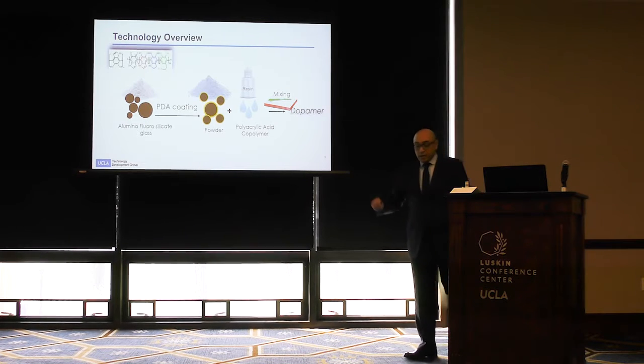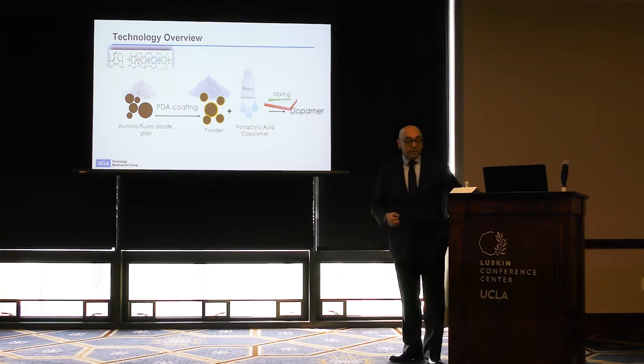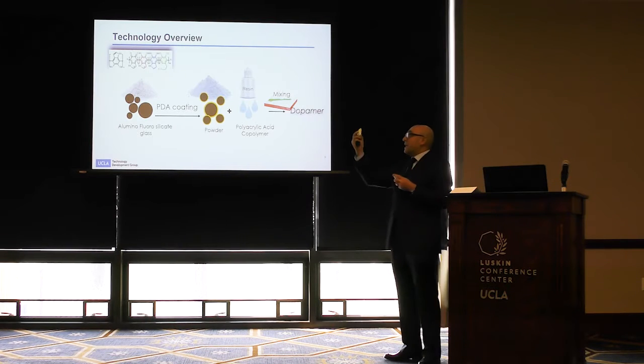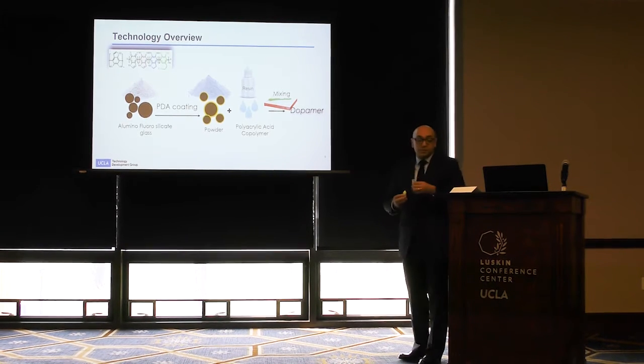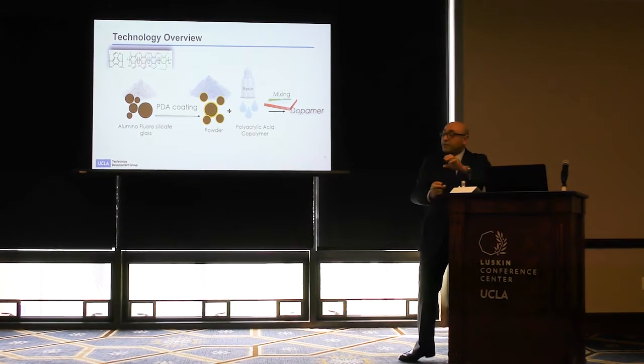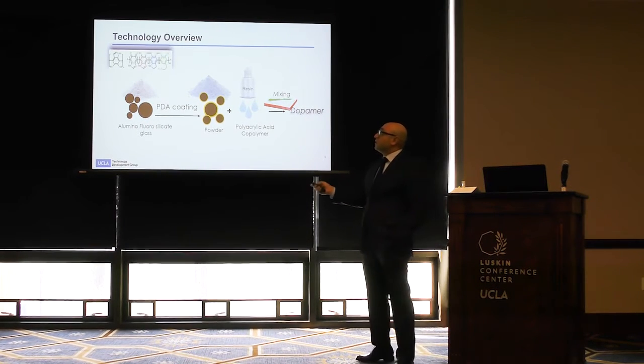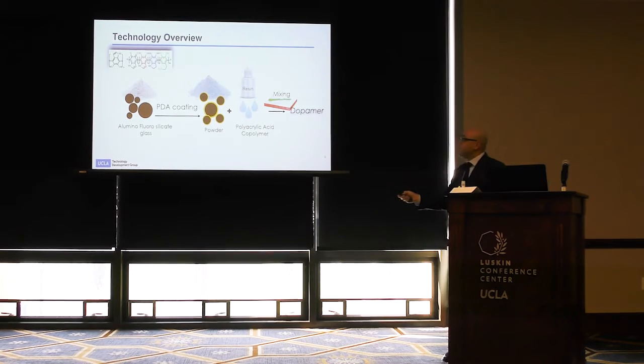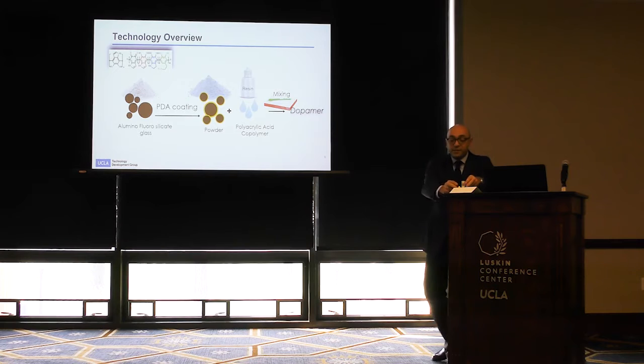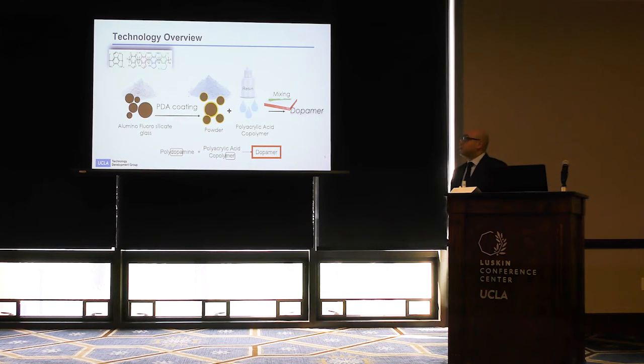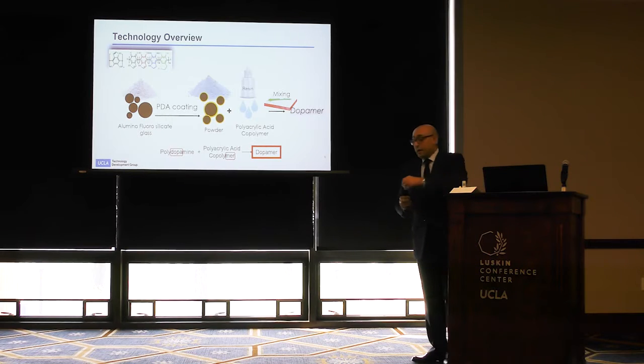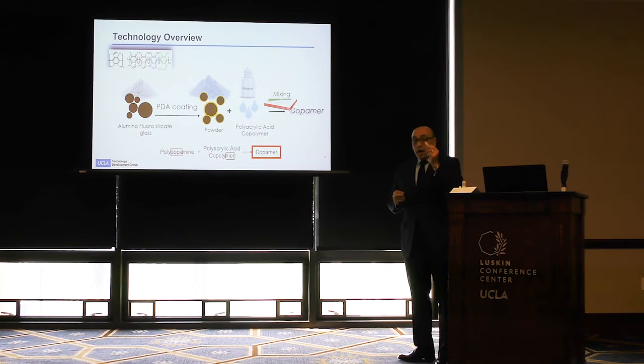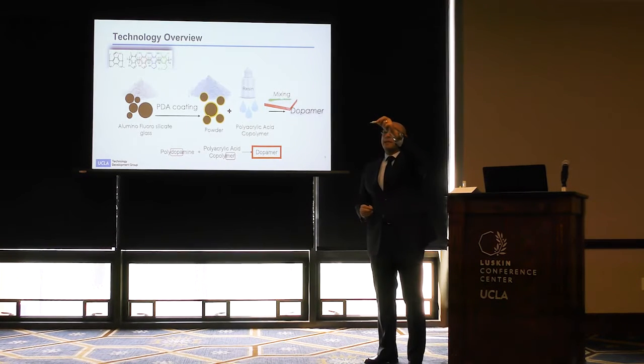Just a little bit about the scientific background and technology. Our Dopamer is based on a powder and a liquid. The powder is based on fluoroaluminosilicate glasses, which are surface modified with polydopamine technology, and the liquid is based on polyacrylic acid. So when the dentist mixes this powder and liquid, we get a cement, a hard material, which is our Dopamer, based on the polydopamine part and the mer part from our copolymer.